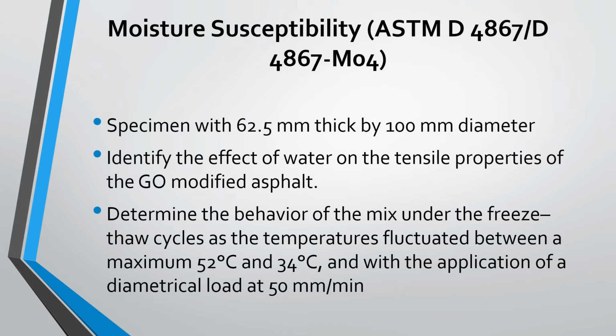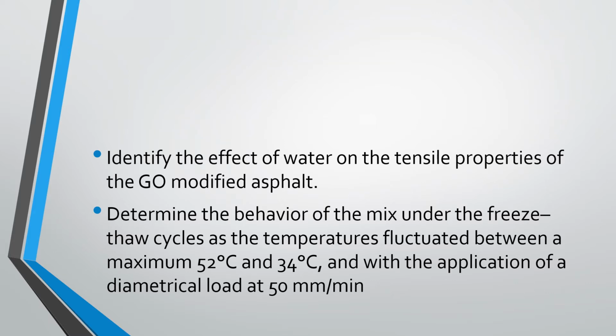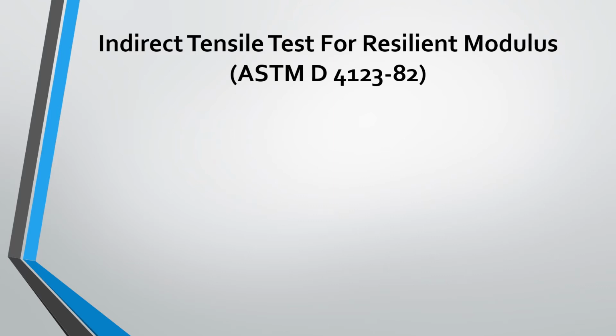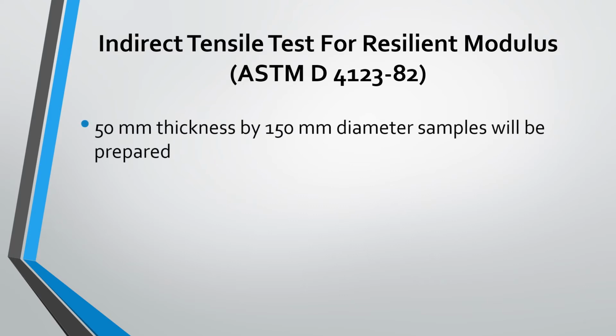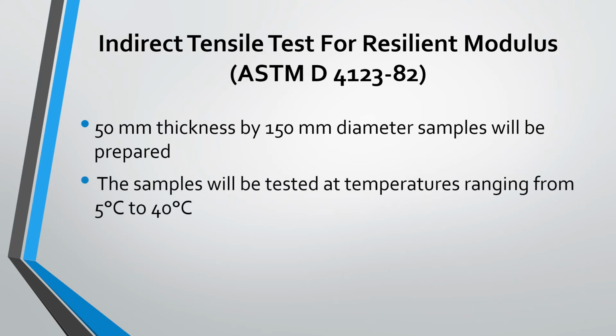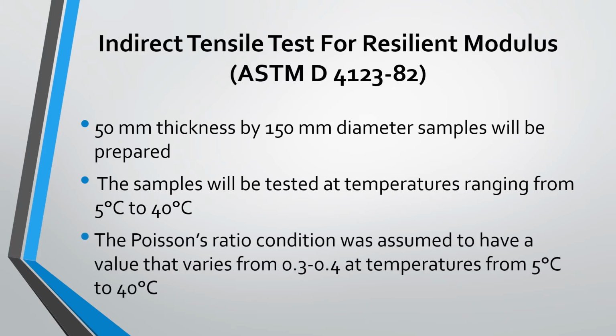In order for us to identify and evaluate the resilient modulus of GO-modified asphalt, the indirect tensile test for resilient modulus of ASTM D4123 will be used. A 50 mm thickness by 150 mm diameter sample will be prepared. The samples will be tested at temperatures ranging from 5 degrees to 40 degrees Celsius. The Poisson's ratio was assumed to have a value that varies from 0.3 to 0.4 at temperatures from 5 degrees Celsius to 40 degrees Celsius.